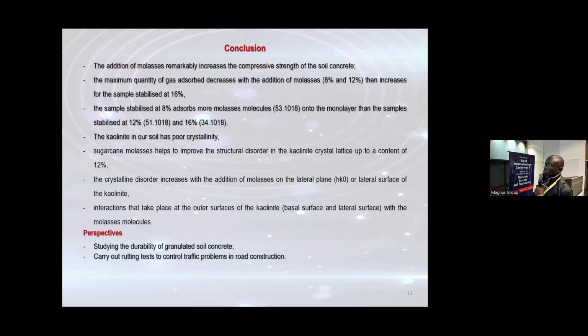At a molasses content of 16%, the water content thickens the water film, the effect of molasses lubrication on the grain is weakened, and the molasses moves away from the surface of the grain, and the adhesion force between the grains is weakened. We note that all the forces involved in this mechanism are physical. Conclusion: the addition of molasses remarkably increases the compressive strength of the soil concrete.